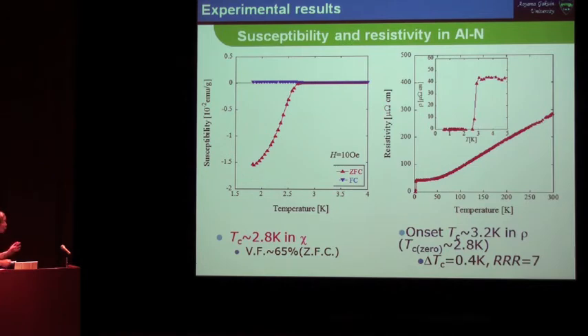So almost everyone has a strong doubt that this superconductivity is due to the aluminum, but aluminum's usual superconducting transition temperature is lower than 1 Kelvin, so it is pretty sure that this is a new superconductor in aluminum nitride.